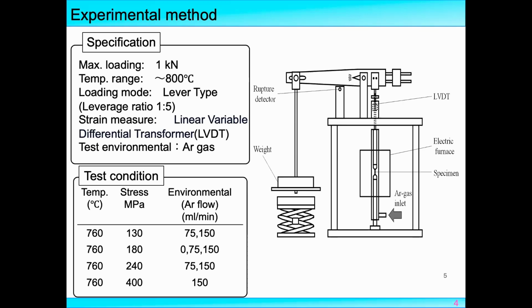Due to the titanium and aluminum alloy having good high temperature properties, we choose 760 degrees to conduct the creep test. The stress level is given here. We use 4 stress levels to test the creep strength. In order to investigate the oxidation effect on creep life, we use 3 Ar flows to conduct the creep test, which are 0, 75, and 150. The unit is given here.